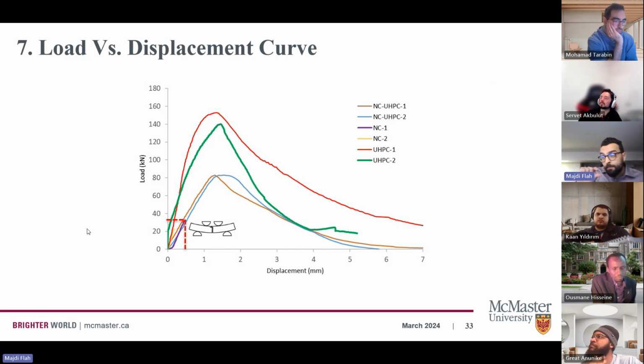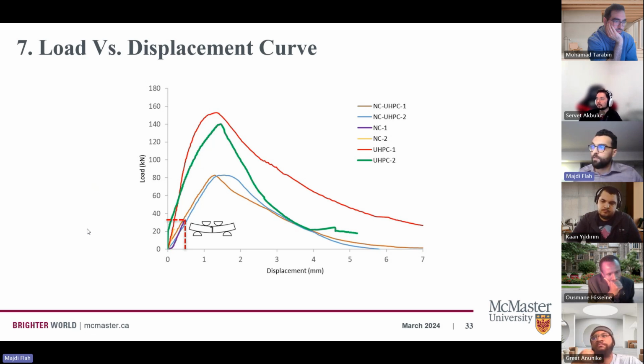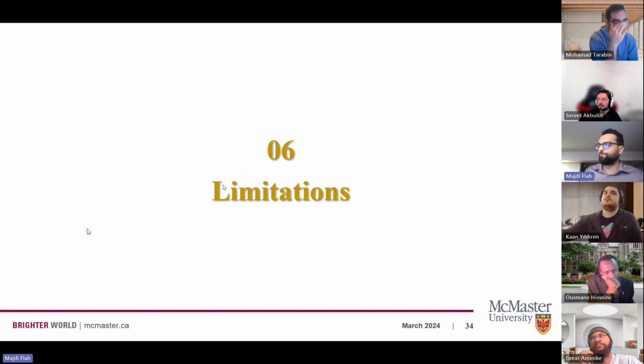And then we start seeing some strain or displacement hardening effect despite the size of fibers we have. But if we had, for example, hooked end fibers, we're going to have a better performance. Maybe we're going to have some displacement hardening as shown in our lectures. So for the normal strength concrete UHPC, the load was around 80 kilonewton, and then for the second specimen, we had a better behavior by getting more displacement hardening as shown in here.